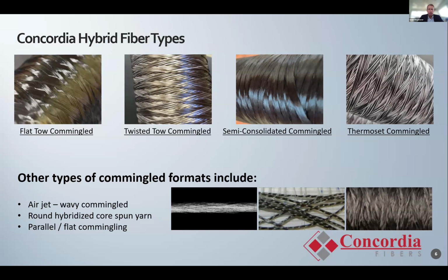Then we have our twisted tow. It's going to be a little bit rounder. We can also control the amount of twist. Some customers like to have the ability to push on a tow, let's say, for 3D printing applications. And then the third picture across the top is our semi-consolidated. It looks and feels more like a slit tape tow. The width tolerance isn't as accurate as a slit material, but the volume fraction down the length of the tow is very well controlled and works out very well for thinner applications.